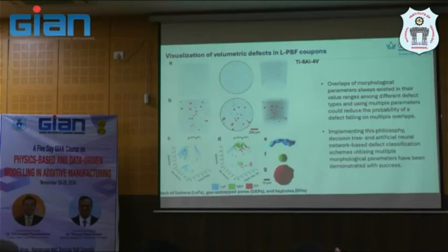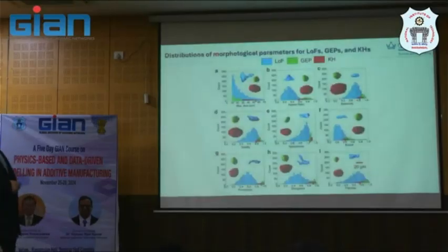Then they try to classify and map, because from the aspect ratio you can basically classify what type of porosity it is. On the color code here, if it's rounded and small, it will be green. A big size is red. Green means probably, if you read this paper carefully, that it's okay, not too harmful, but red is very harmful, it's too big. The elongated is somewhere in between, and there's some overlapping in the morphology parameters as well, because sometimes you cannot cluster them very well. But what they did is this. If you look at different samples, this is a distribution you may get from the classification.